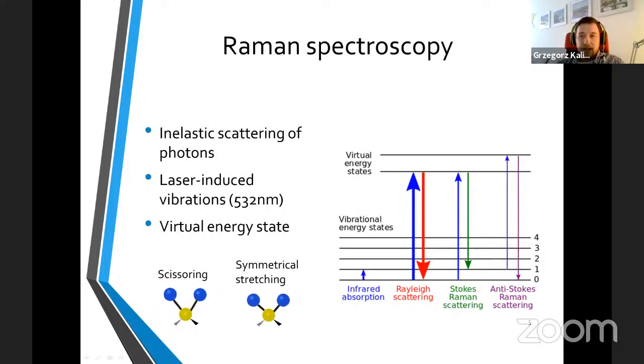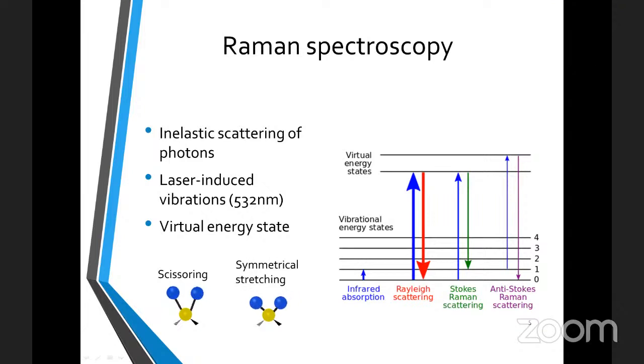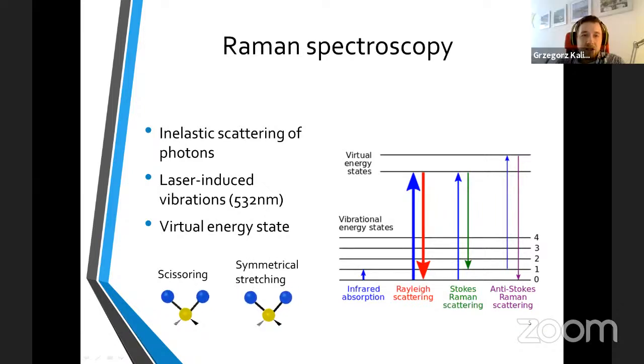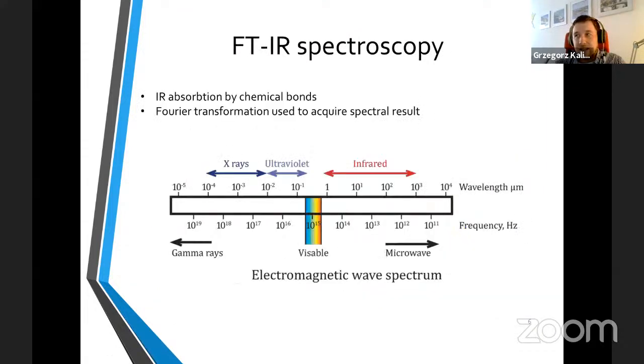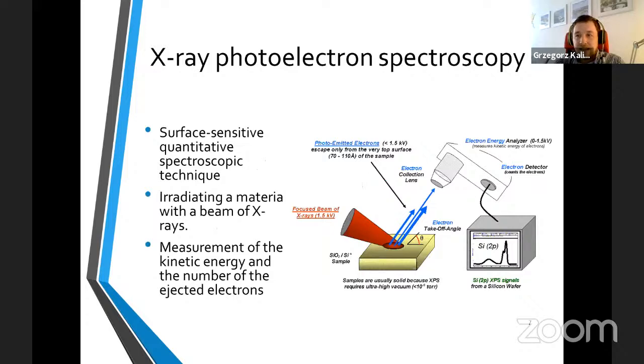In our research, we focus mainly on Raman and FTIR spectroscopy. Raman is about inelastic scattering of photons, named after the Nobel Prize winner. We use laser-induced vibrations with a 532 nanometer laser, putting the molecule in a virtual energy state and later measuring the radiation. FTIR is different in principle because it is about infrared light absorption by chemical bonds, and we used Fourier transformation to acquire spectral results. The third spectroscopic method is XPS. This is a more surface sensitive and quantitative technique, used by irradiating the surface area with soft X-rays and measuring the kinetic energy and the number of ejected electrons.